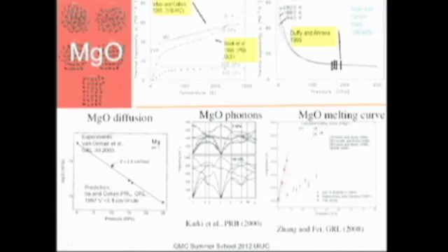This is work from many years ago now, but for example, if we look at something like the thermal equation of state, like the thermal expansivity, we get results really within experimental error, not only at zero pressure, but also at very high pressure. If you look at the thermal expansivity here measured in shock experiments up to almost 2 megabars, these show the error bars from the experiments. You see the calculations, done some years before the experiments originally, really agree quite well and go right through the error bars.